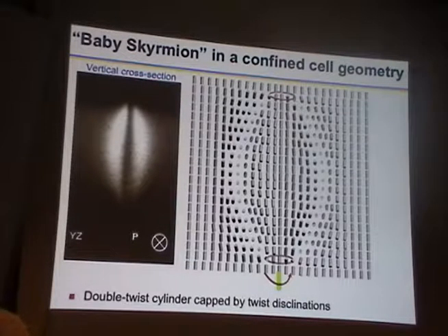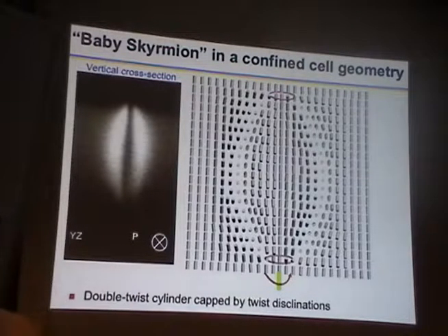And so next, I would like to demonstrate a series of structures that we can generate in confined chiral nematic liquid crystals, again using different types of laser beams, just by controlling slight, tiny details of generation, such as laser power, whether we use confining glass plates with transparent electrodes or not, because that will influence heating of the sample and so on.